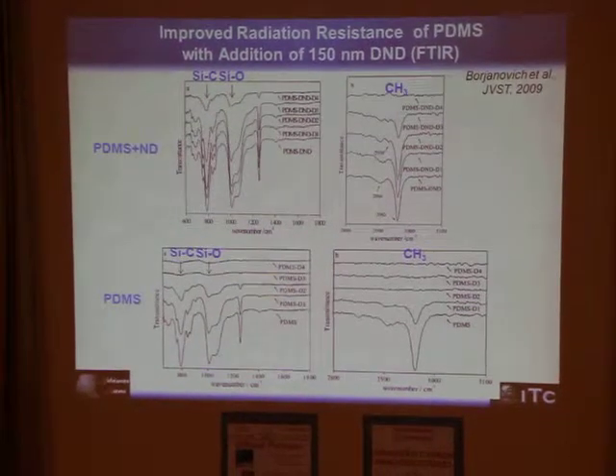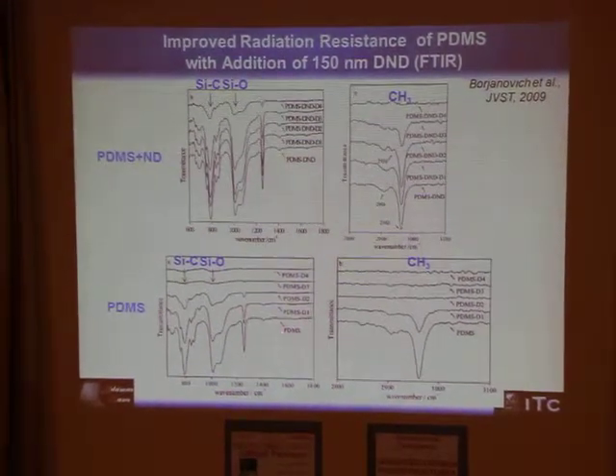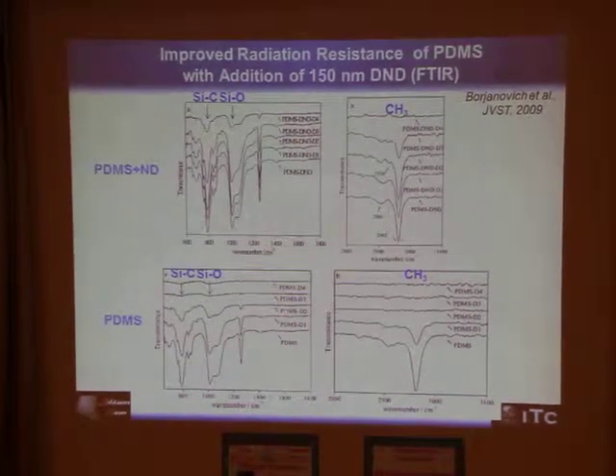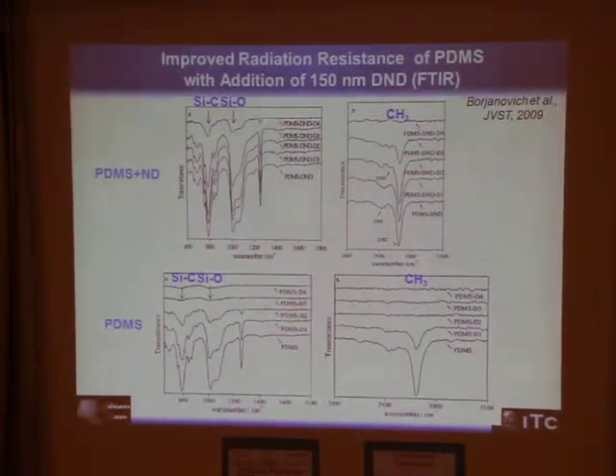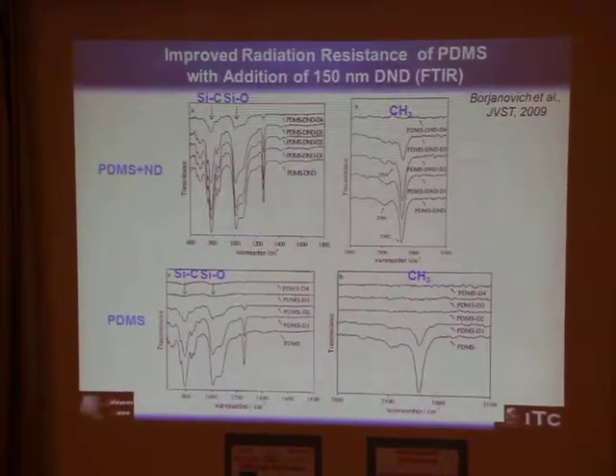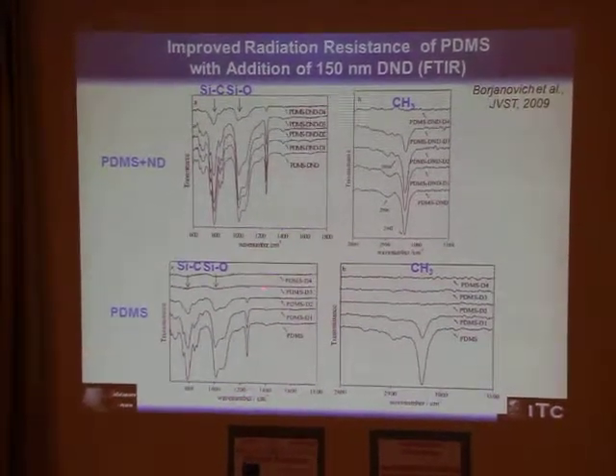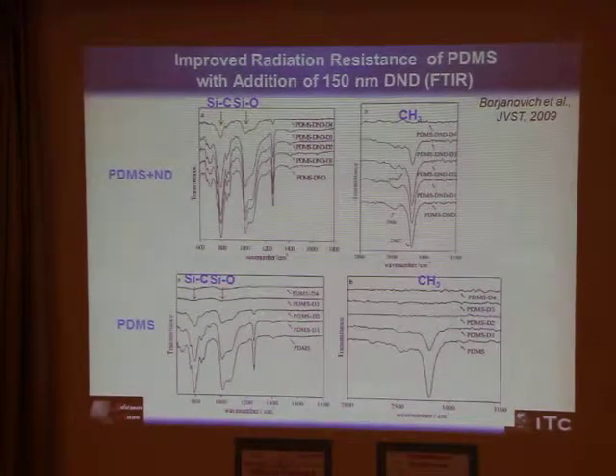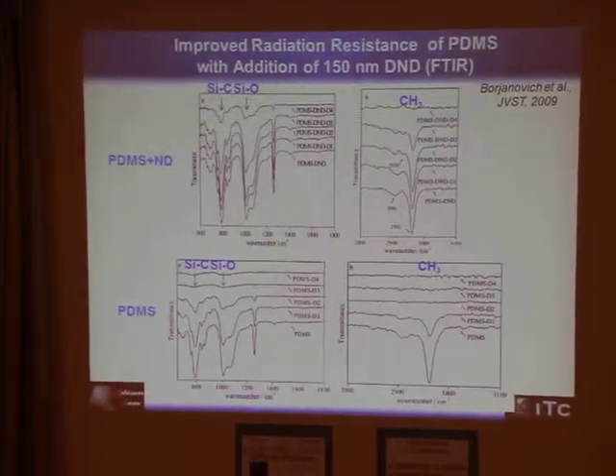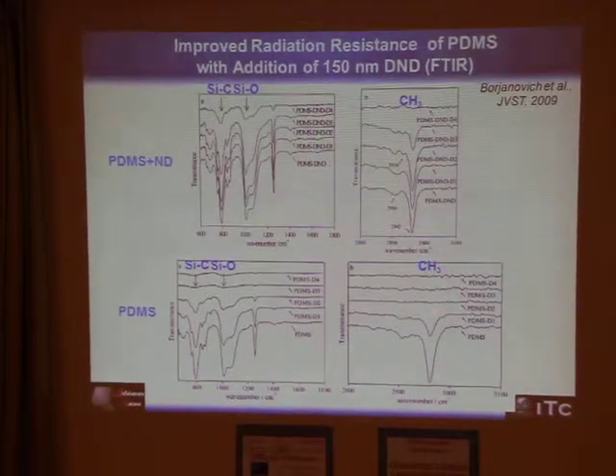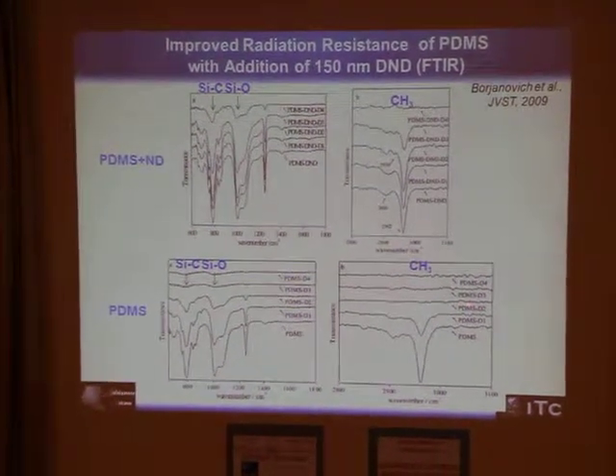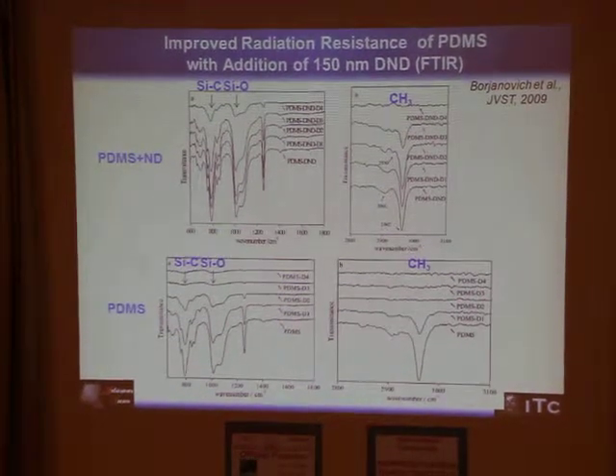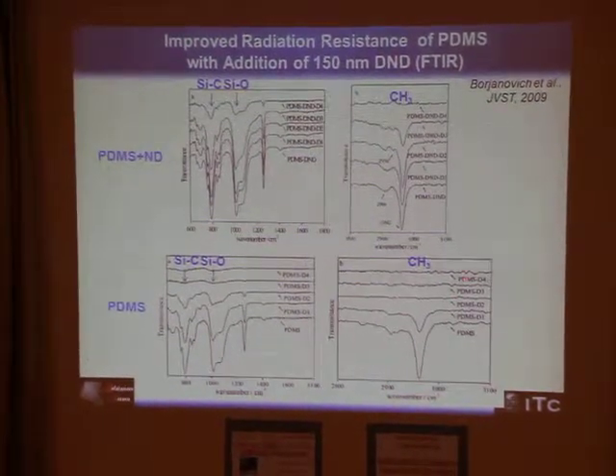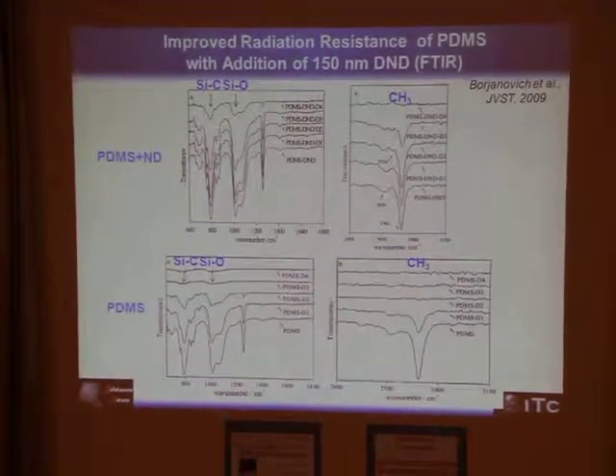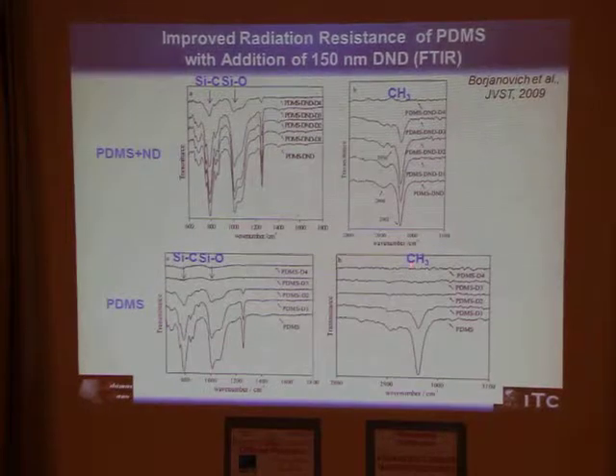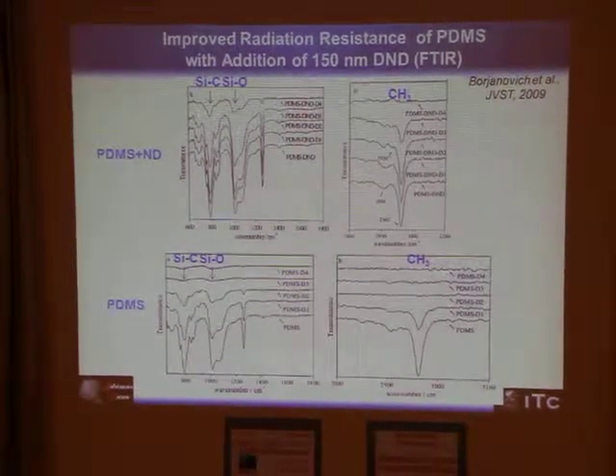So you can see that with increasing proton irradiation dose, at dose 3, D3, characteristic peaks practically disappear for pure PDMS, the same of course for higher doses. And for the CH3 group, you can see that hydrogen is stripped out, no CH3 groups exist at doses 2, 3, and 4. So that is what happens with pure PDMS, how it loses its structural integrity.